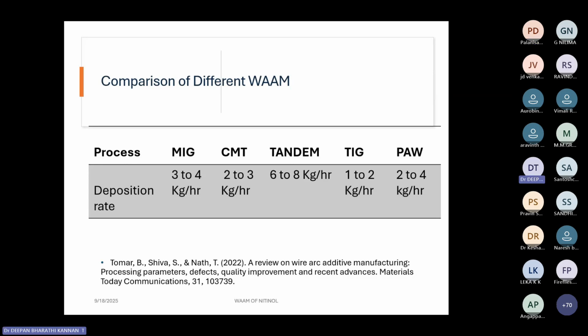Okay, thank you. So in this table, you could see that comparatively, this twin arc, that is tandem, is having around 6 to 8 kilograms per hour, whereas MIG is having around 3 to 4. CMT, since we are focusing on minimizing the spatter and the heat input, is around 2 to 3 kilograms per hour. TIG, as we all know, is one of the cleanest arc welding processes, so the deposition is on the lower side, but the quality may be on the higher side. If the deposition rate is not a concern, people can prefer TIG-based wire arc additive manufacturing for building shapes in nitinol shape memory alloy. It is only around 1 to 2 kilograms per hour, whereas plasma arc welding is around 2 to 4 kilograms per hour. So according to our requirement, people have explored CMT, and people have started to use twin arc wire also with nitinol shape memory alloy.